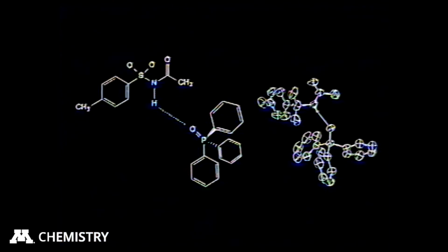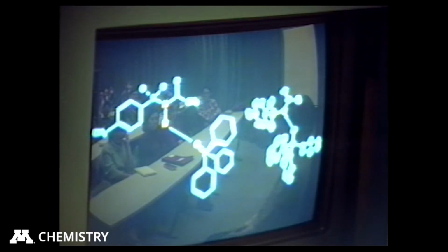Okay, so our approach was to look at host and guest molecules that would form strong hydrogen bonds to one another. The idea is, if you take a molecule like triphenylphosphine oxide, which has a very strong proton acceptor on it, and put it in the presence of a molecule where none of the functional groups on that molecule are better acceptors than this one, that in solution, that oxygen will find that hydrogen. So they'll pair up in solution and a co-crystal will form. And in fact, this has worked in many, many systems. I mean, probably we're close to hundreds where this idea has worked, just that simple idea.